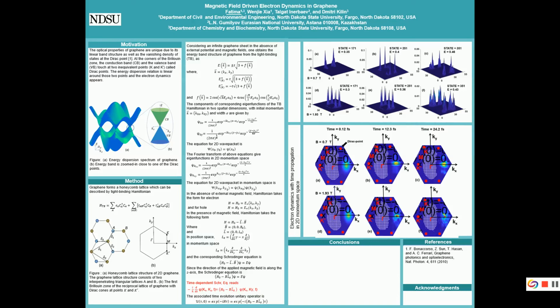Here, each graphene atom has three nearest neighbor carbon atoms and other next nearest neighbor atoms. And this is the tight-binding Hamiltonian of the graphene. This first term for nearest neighbor carbon atoms and this second term for the next nearest neighbor carbon atoms. If we consider only nearest neighbor carbon atoms and solve it, we can get this dispersion relation. And here we have two signs, positive and negative, positive for conduction band for electron and negative for hole in the valence band.